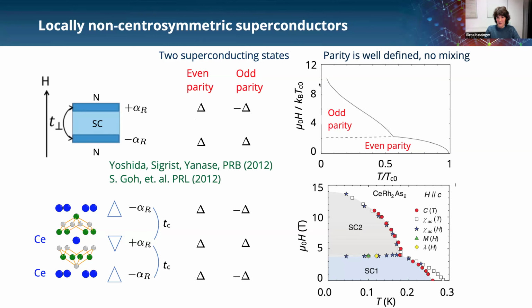And they predict a phase diagram, temperature and field, where you start with an even parity state at low fields, this is Pauli limited and so suppressed. And at some point, you will have a switch, a first order transition to an odd parity state, which survives up to high fields. Okay, and that's actually how we understand our phase diagram. And the reason is that our system, although we start from the bulk crystal structure, is very similar. And we can even write down a Hamiltonian, starting with all allowed terms in the local symmetry of the cerium. And we end up with a very similar model as before. And so we have these two even and odd parity superconducting states.